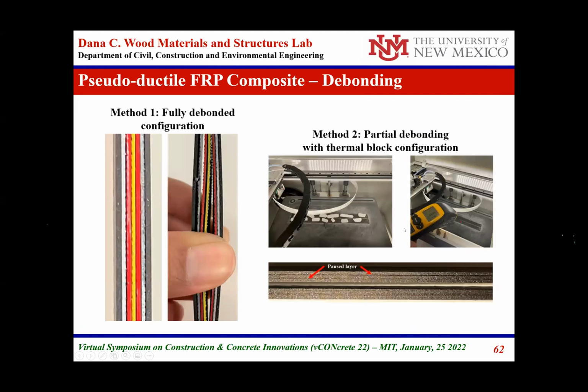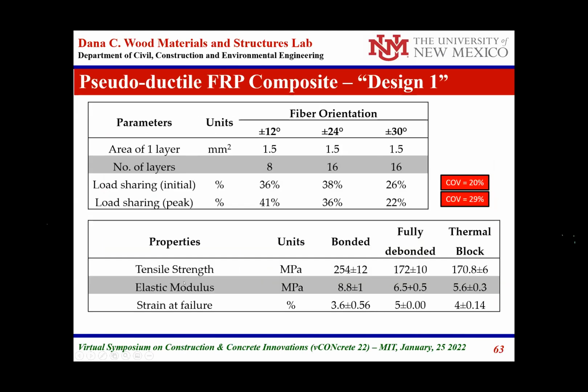So we tested this in modeling, then we started doing testing. We started to examine the significance of debonding some of the layers to allow it to work, because the layers' behavior when bonded is different than debonding. We used fully debonded layers, and we also used partial debonding using thermal blocks during the 3D printing to promote the debonding of the material.